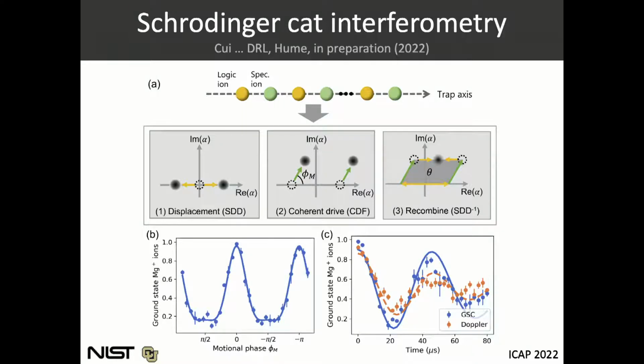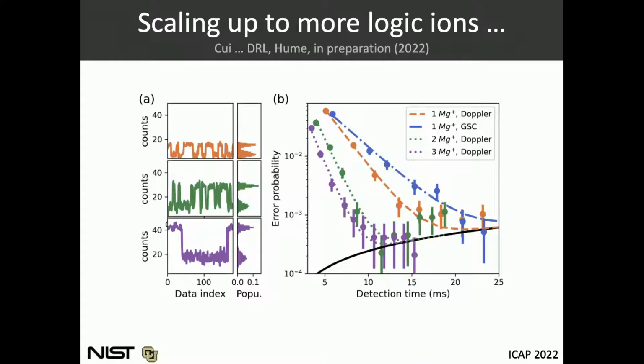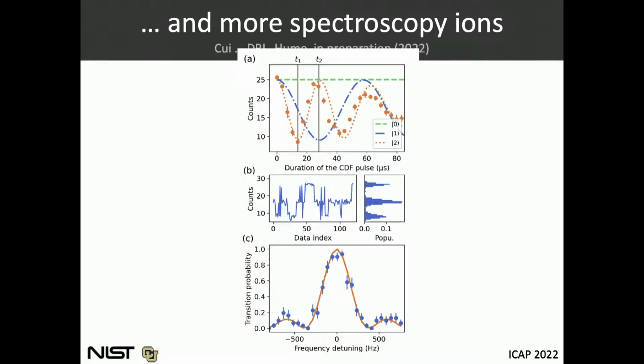We can read out that motion using this geometric phase gate type scheme in which we prepare a cat state, a motional cat state of magnesium. We apply this spin-dependent force, and then we close this interferometer. And so with this, we've been able to read out, well, one, more efficiently, so we can read out a single ion faster. But probably more importantly, we've been able to read out more than one aluminum ion.